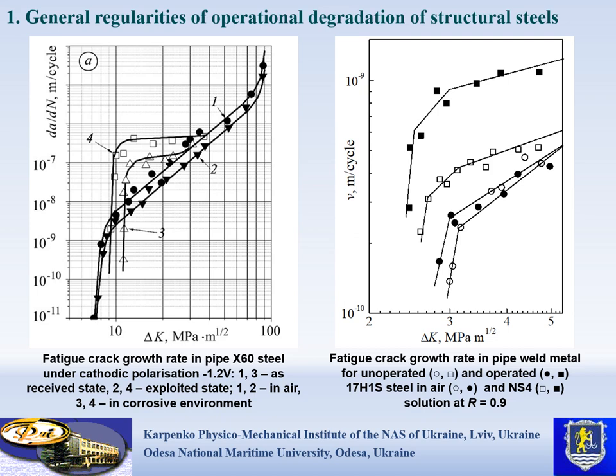Regarding the middle part of the fatigue crack growth rate curve in air, it is less sensitive to operational degradation. However, corrosion environment will increase the crack growth rate more intensively for exploited steels. And an increase of stress ratio increases sensitivity of the crack growth rate to operational degradation.